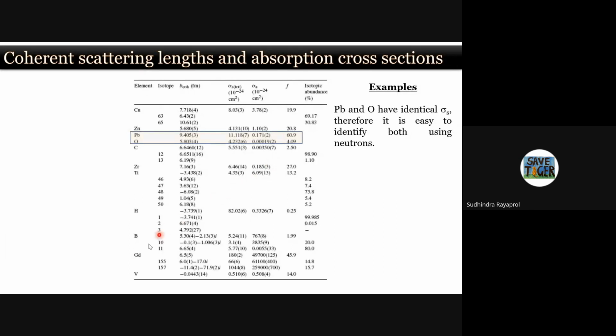Okay, in the same example, you can see that in the case of gadolinium and boron, the absorption cross-section is much higher than the scattering cross-section. So if you have gadolinium or boron or vanadium in your sample, it is very difficult to get the scattering from these elements, because they can absorb neutrons more than they can scatter.